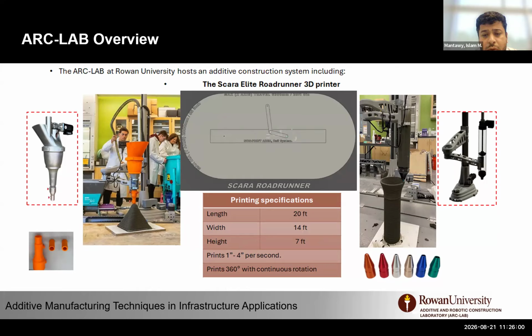We have two systems. On the right side, we call it the closed system because it uses a syringe tube. And the left side is the open system, from the mixing to the pump to extrusion, using the auger system that regulates the extrusion rates. We can print now from a 5 mm nozzle up to 2-inch nozzles.